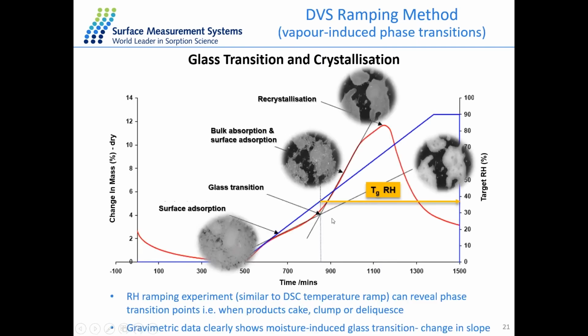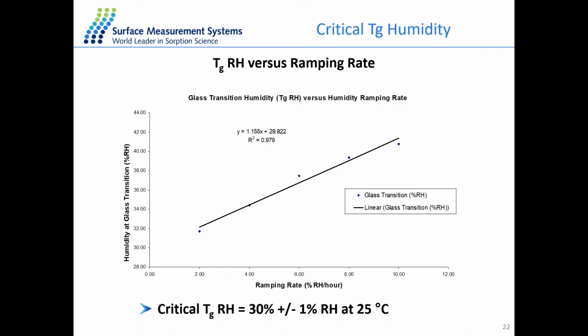And this is the experiment we performed at a 5% per hour ramping rate. And if we change the ramping rate, we can then get a correlation between the ramping rate and the glass transition humidity. And from the intercept of this line, we will then get a critical glass transition humidity at 0% ramping rate. And this is important for the storage of the lactose sample. So above this humidity, the sample will go through crystallization.